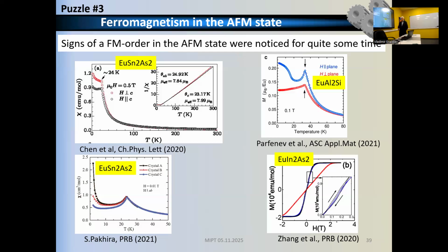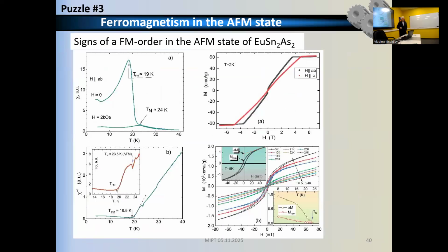The problem is that we deal with some ferromagnetism in our sample, and people said, okay, there might be impurities. But if you put some numbers, you immediately conclude that it's unrealistic for the highest purity materials. Now, to explore this effect, we have taken, from the point of view of what I said, the worst sample, where these ferromagnetic type signatures are the largest. So we have a large number of samples, and we selected some, and indeed, it shows a magnetization curve like this with a well-pronounced non-linearity in the vicinity of the zero field. So we zoom in on this non-linearity and see the hysteresis effect.